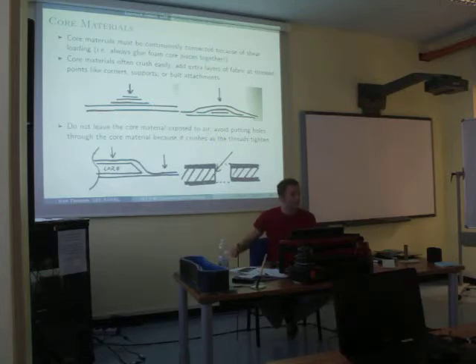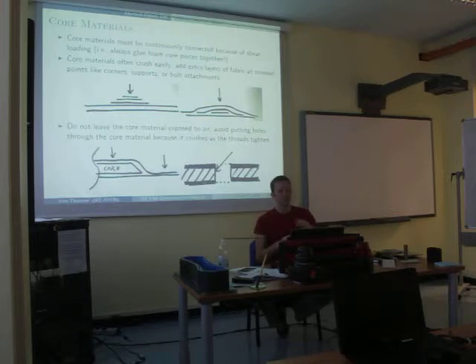Core materials. The piece that I showed you that was broken, of the carbon fiber and honeycomb, should emphasize a couple things here. Core materials must be connected continuously because of the shear loading. You can't just put 2 pieces of foam together without gluing them and then put fiberglass on top, because that becomes a point at which the shear loading moves the 2 pieces relative to each other, and the fibers on the surface will begin to pull off of the core material, and you have a failure. Once that starts to happen, you can have bending, buckling, and everything starts to fall apart. So glue your foam pieces together, glue your core materials together, and make sure you have a good bond between your core material and your fabric on the top.